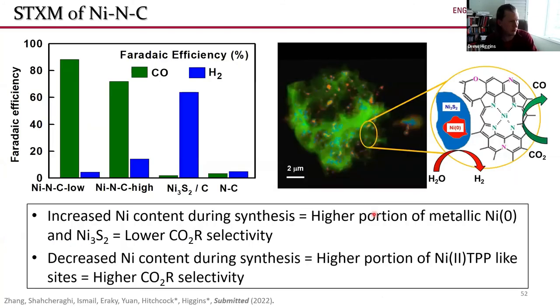We correlated this characterization with results of electrochemical CO2 conversion. And ultimately what we arrived at, without diving too much into the details, is that these catalysts consisted of these nickel TPP-like structures all within this carbonaceous matrix that were very good at converting CO2 into carbon monoxide. And those particles consisting of metallic nickel or nickel sulfide, some of them were blocked by carbonaceous layers, but some of them were exposed.